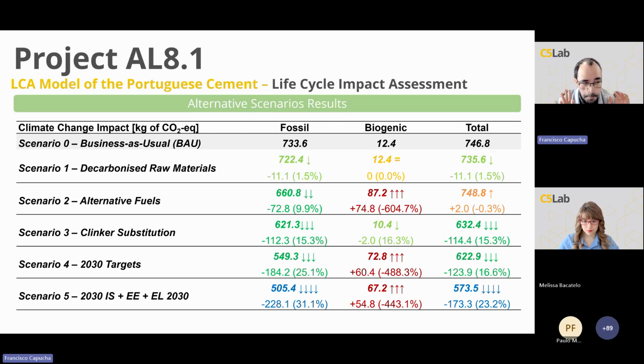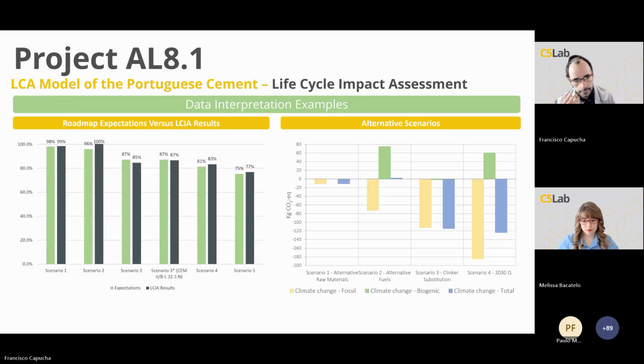The replacement of clinker produced the most significant reduction due to the ambitious target of 65% average clinker content. And finally, we can also conclude that the inclusion of energy efficiency measures further amplifies the reductions observed. When examining the variations in CO2 emissions, the effectiveness of clinker substitution can be observed, thus confirming the importance of controlling this ratio as the most important and most effective measure within the cement industry, other than carbon capture. We notice also the counterbalancing effect of the use of alternative fuels caused by the increase of biogenic emissions. However, with the new standards for assessing the environmental impact of cement, nowadays the alternative fuels used would actually produce a more robust reduction, so the results will be even more amplified nowadays.